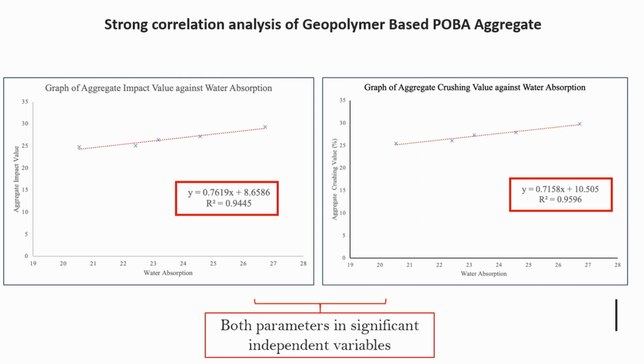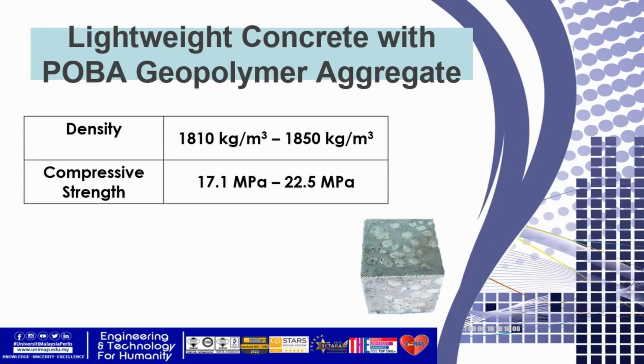For the performance of POBA geopolymer aggregates in lightweight concrete, as you can see here, the density of the lightweight concrete will be in the range of 1,810 kg per meter cube to 1,850 kg per meter cube. And the compressive strength achieved up to 22.5 megapascals at 28 days.